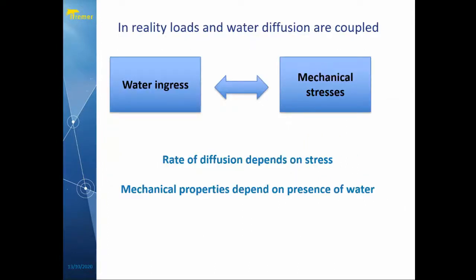Next slide, please. And then the other point to underline is that in reality, we can put materials in water, look at how they degrade. We can also look at the mechanical behavior. But in reality, these are acting together. So we have water ingress, permanent immersion, and we have mechanical stresses which are constant or variable throughout the lifetime. And the rate of diffusion of the water also depends on the stress levels. So if you get higher stresses, you tend to accelerate water ingress.